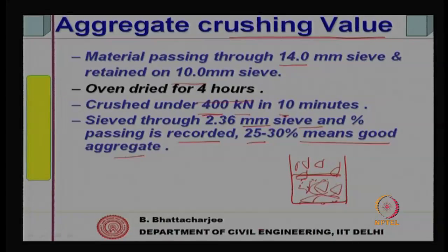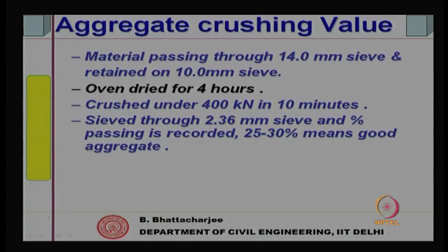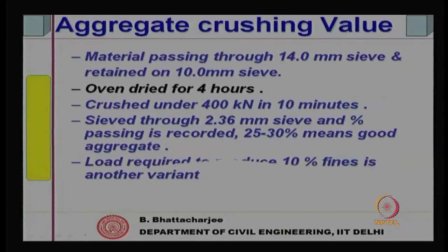25 to 30% means good aggregate. If it is high, 40-45%, then it is not so good aggregate. Comparatively, 25 to 30% is good aggregate, so it can be used in concrete. Therefore, this is used